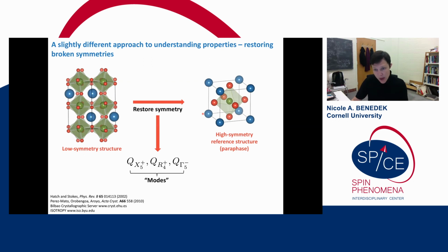So we can expand the energy of the paraphase in powers of these modes. And the form of that expansion gives us a lot of information about how various modes are coupled together, and about the mechanisms through which symmetry breaking happens.